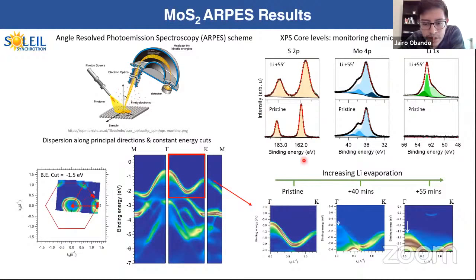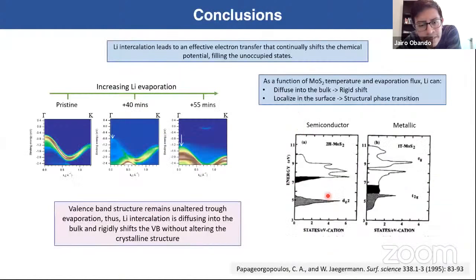Then we repeat the same measurements after evaporating different amounts of lithium, and what you can see here in this part of the slide is how the valence band evolves as we increase the evaporation time, and therefore the amount of lithium that we are putting on the system. Depending on the temperature of the substrate and the flux of lithium evaporation, we can get into two different situations. One in which the molybdenum disulfide structure is able to diffuse all the lithium homogeneously into the bulk, that is, to intercalate it, and another one in which part of the lithium diffuses, but another part remains stuck at the surface. In our case, we are in the first situation, in which lithium is homogeneously intercalated in the structure, and an electron transfer process occurs.